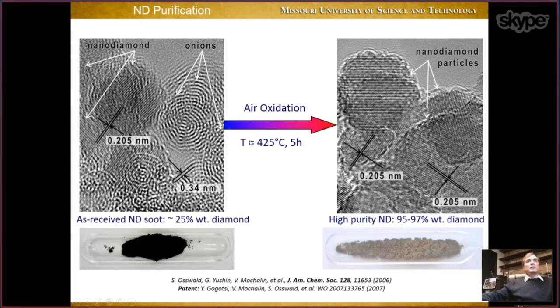So it was very critical to discover this particular temperature, and then we published this paper in 2006 in Journal of the American Chemical Society, and now this technique is one of the most widely used purification strategies for diamond. And then after purification, you can see immediately visually that the appearance of the material changes, it becomes much lighter compared to this. And if you put it under transmission electron microscope, you will see that the material is mainly made of diamond. There is almost no non-diamond carbon at all. So by using air oxidation, we can go from about 25% of diamond in this material in detonation soot up to 95–97% of diamond. So it's one of the purest nanodiamond I've ever seen.